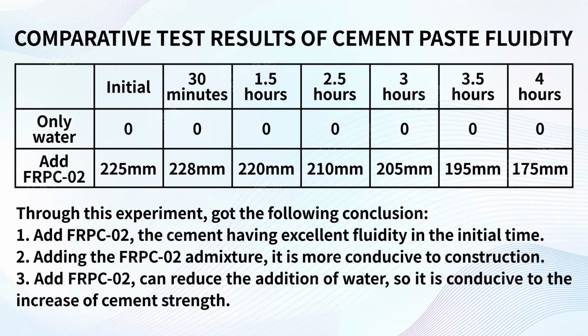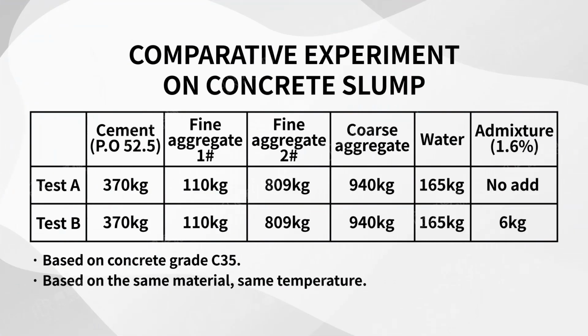1. Add FRPC-02. The cement has excellent fluidity at the initial time. 2. Adding the FRPC-02 to the admixture is more conducive to construction. 3. Add FRPC-02. It can reduce the addition of water, so it is conducive to the increase of cement strength.